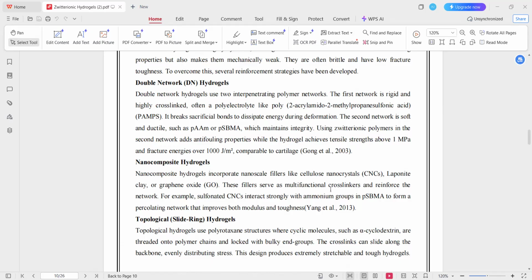Double network zwitterionic hydrogels can achieve tensile strength above 1 megapascal and fracture energies exceeding 1000 joules per square meter. These values are comparable to natural tissues such as cartilage, making them suitable for biomedical implants and soft tissue substitutes.